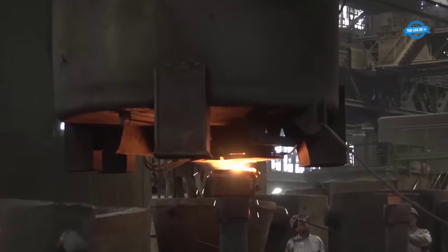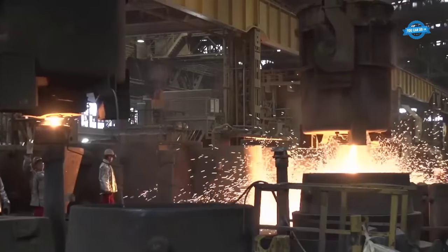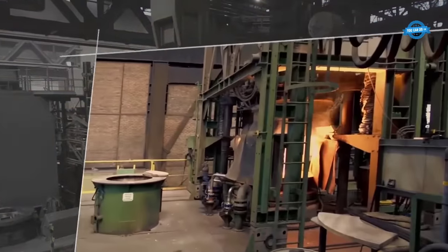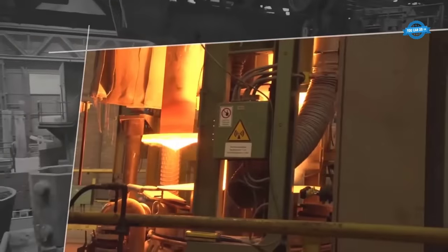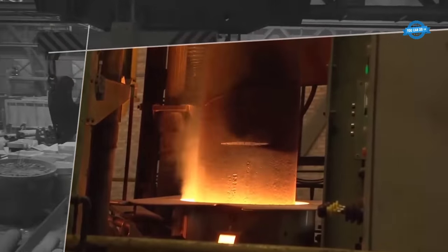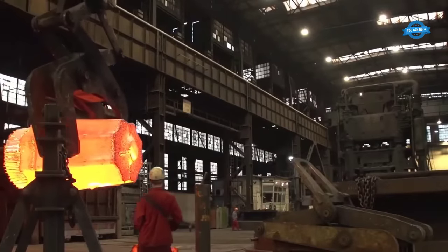After a purification rinse, the mass is cast into blocks, optimized for weight and size to match the subsequent forging processes. The largest forging ingot weighs 76 tons and is produced from two heats. To ensure maximum purity and homogeneity, an electro-slag remelting process can be integrated before the forging operation. The smelted mass is heated up to 1200 degrees Celsius in the forging furnace. The forming process then takes place on the Mega Newton press, with the manipulator grasping the forged end to initiate the actual forging operation.